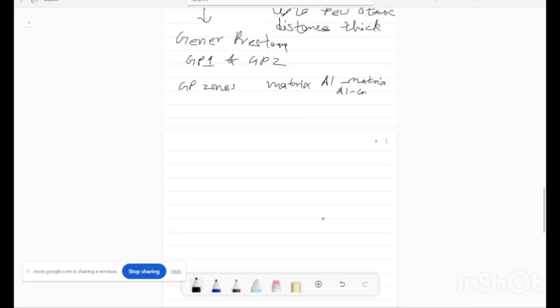That lattice strain will hamper the dislocation motion. So if the dislocation motion is hampered, then more stress will need to be applied for further deformation, and the strength is higher. So the strengthening happens. Lattice strain results in strengthening.